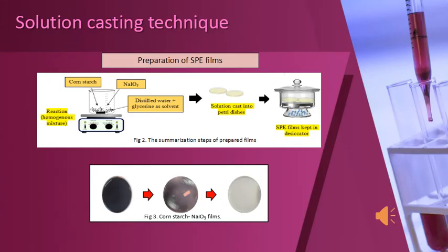Solid polymer electrolyte films were prepared using a simple method known as the solution casting technique, and this method is summarized in figure 2. As you can see, the cornstarch and sodium iodate are mixed together with distilled water and glycerin until a homogeneous mixture is formed. Then the solution is cast into a petri dish at room temperature until the film is formed. For further drying, the SPE films are kept in a desiccator filled with silica gel.